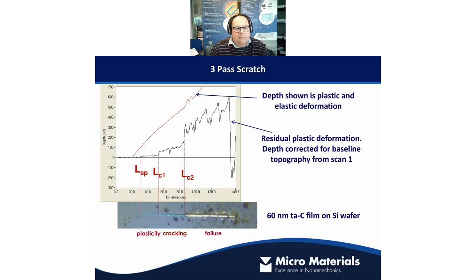But there are some events that occurred before that. If we go back to the first event, just here, this LEP is really the transition of our contact from fully elastic to elastic plastic. So we called it load elastic plastic. What you can see is that the pre and post scratch topography traces actually separate at that point. Until that point, our contact was elastic. On load, we had a total measured deformation which was thicker than the coating. So the sample had elastically flexed to something in the region of 100 nanometers, but that was completely elastic. Anything beyond that, we're into plasticity.